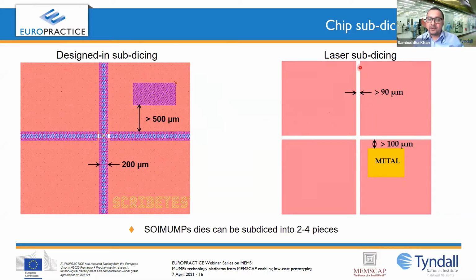Laser subdicing is definitely much easier, because for laser subdicing, you just need to define a laser subdicing mark on the SOI level, and this is 90 micron. And by the way, I forgot to mention that from the dicing line, say you have a device designed here, and at the same time you have a trench in this place, so the distance from the dicing trench to the design trench should be a gap of at least more than 500 micron. Similarly, for laser subdicing, you define the subdicing mark on the silicon layer, and all your metals should be at least 100 micron away from the dicing mark. So in SOI MUMPs, you can finally get 2 to 4 pieces after subdicing a 10 mm by 11 mm die.